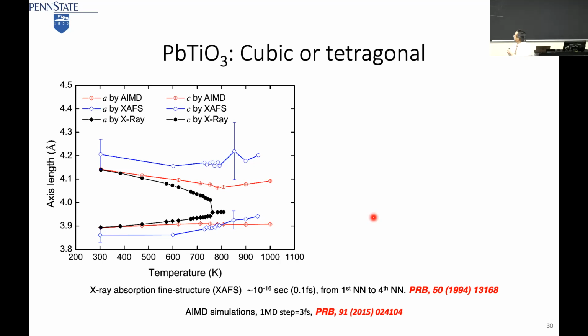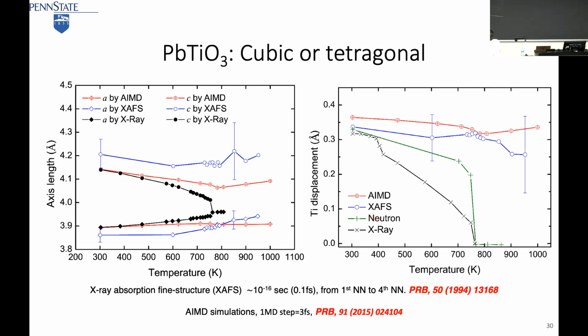So it's cubic some of the time, but most of the time it's tetragonal. So we put a height on that. You look at the polarization, same thing. Neutron and X-ray give you zero polarization above the transition temperature, but if you look at the individual titanium atoms, they are always displaced. So that's your resolution. If you are slow, it's cubic. Fast, it's tetragonal. So both are correct. But the question is, can we predict it, right? So we can predict it.